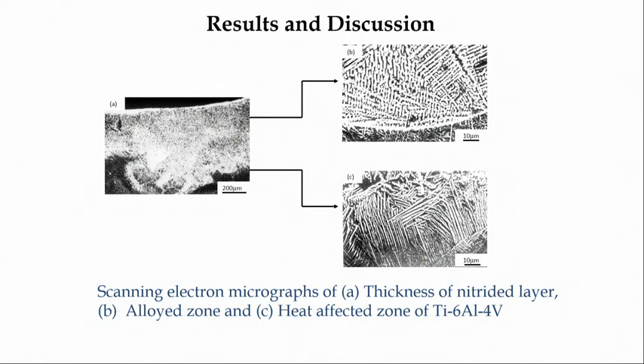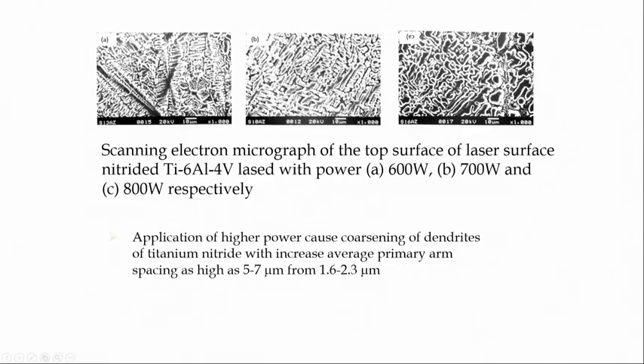Dispersed nitride layer on the surface of titanium. So, the titanium surface is chemically converted to its nitride. If these nitrides were formed by physical vapor deposition or chemical vapor deposition, there would be a very sharp interface and that layer would be very brittle. But as it is carried out by melting and subsequent alloying, the converted part is not purely converted into its nitride, but rather the nitride is in the form of dispersed ions. So, this dispersed nitride layer helps in improving the hardness without sacrificing the toughness.